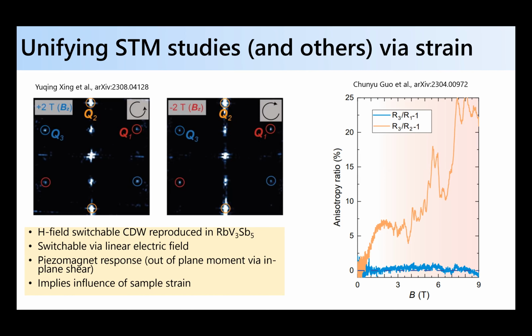And so I think one of the takeaways here is that sample strain can have a profound effect on altering what different groups see via uncontrolled strain effects. And this has been shown in a very complementary work by Philip Moll's group. I think they took the CsV3Sb5 system, cooled it down, and measured in-plane transport anisotropy. They saw a well-defined temperature below which an apparent nematic term turns on, like in-plane anisotropy turning on below, say, 35 Kelvin roughly.